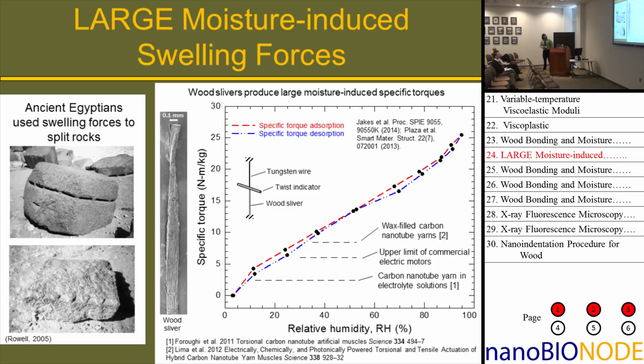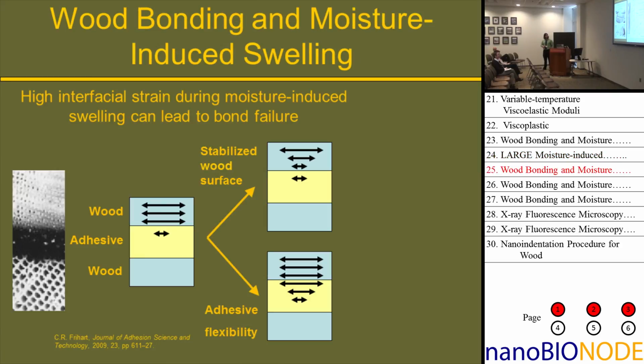And we've also done some work looking at twisting in thin wood slivers, and we built a little device to actually measure the torque that's produced by these wood slivers. We find that on a specific torque basis, as a function of humidity, these wood slivers outperform some recently reported carbon nanotube torsional actuators. So nature's still doing a better job than we can do synthetically. That's more motivation to really study these materials and understand them, because there's still a lot we can learn as material scientists from nature.